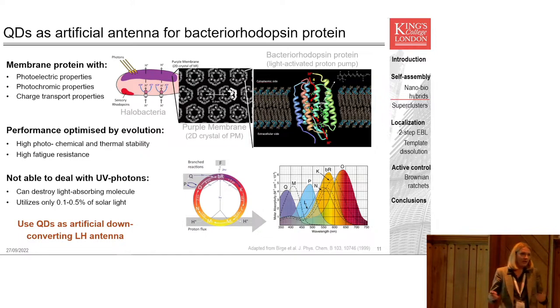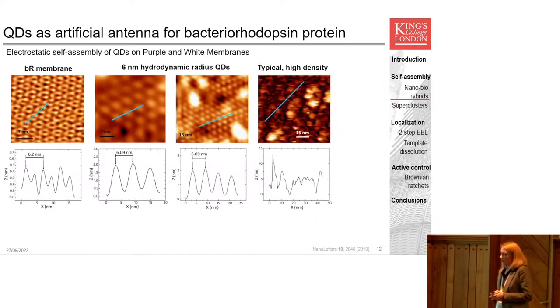So of course, we went ahead and tried to assemble the system, and this is where we ran into a few problems, as you see from this AFM data. So again, this is just electrostatic assembly of quantum dots on top of a bacteriorhodopsin protein. And as you can see, there's no specific attachment of any quantum dots in a general case, whilst you very clearly can see this trimeric 2D crystalline structure of the bacteriorhodopsin protein itself. However, what we found is that if we had the size of the quantum dots just right, we would actually be able to self-assemble it in a very controllable manner, as I show here.